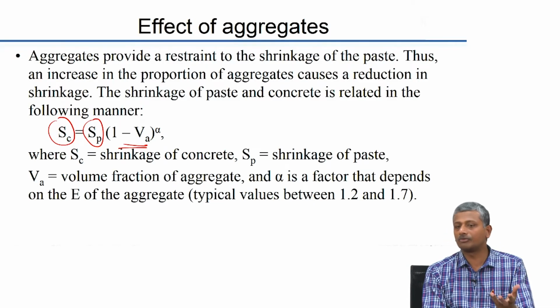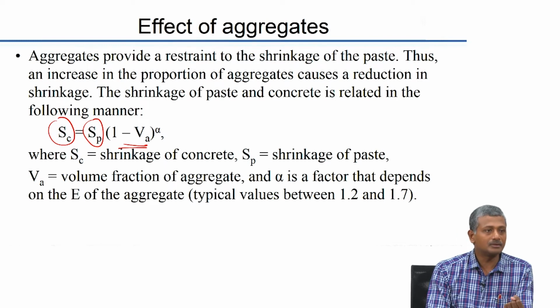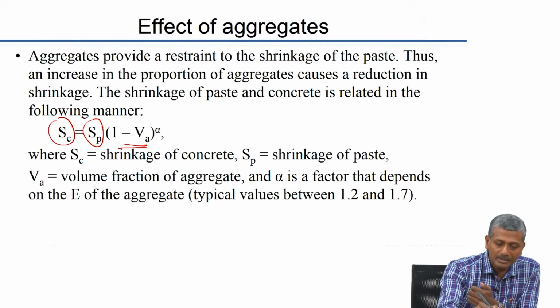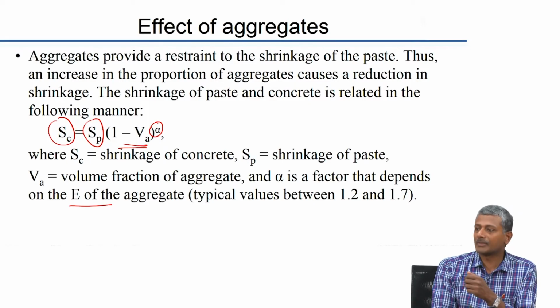So, the greater the amount of aggregate that you have in the system, the greater will be the restraint. And there is also another factor, alpha, which is similar to what you saw in the creep expression also, and this alpha depends on the modulus of elasticity of the aggregate. The higher the modulus, the higher the value of alpha, right. Stiffer aggregate will provide more restraint as compared to less stiff aggregates.